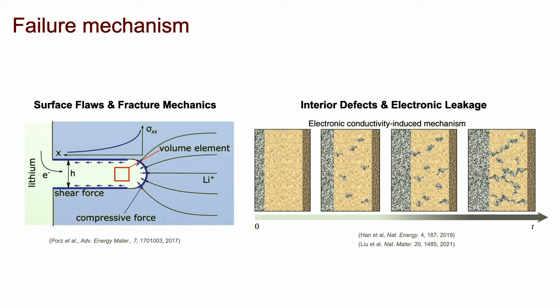An alternative point of view is that there are small spots of higher electronic conductivity through our material, and that leads to plating of lithium metal, and those eventually link up and form this conductive network that shorts the cell. And there's been some evidence of both.